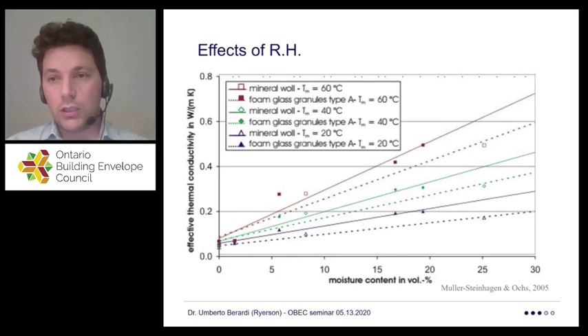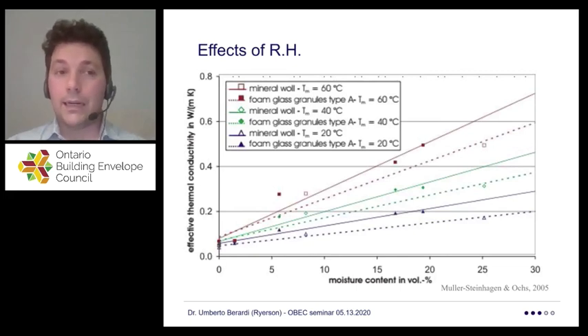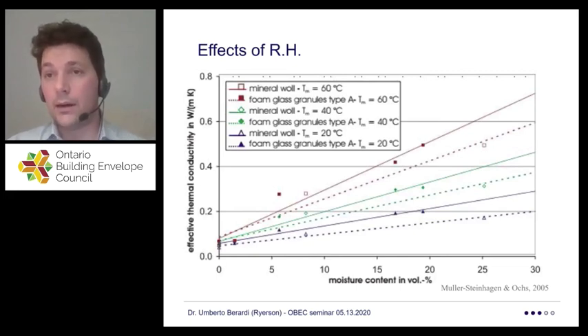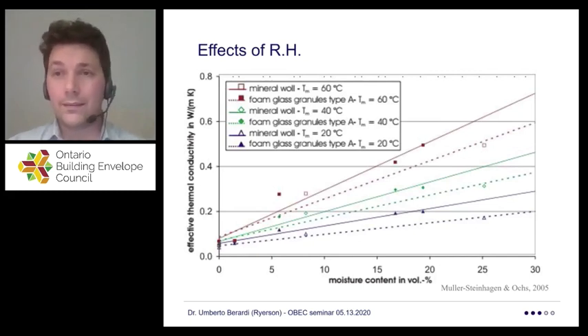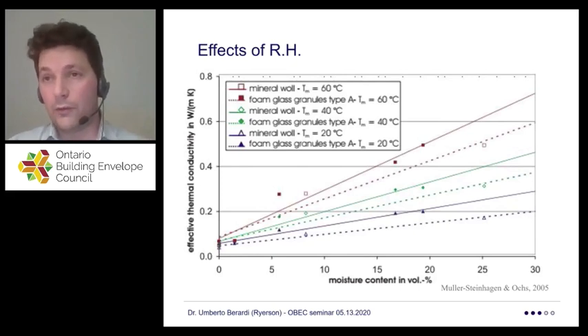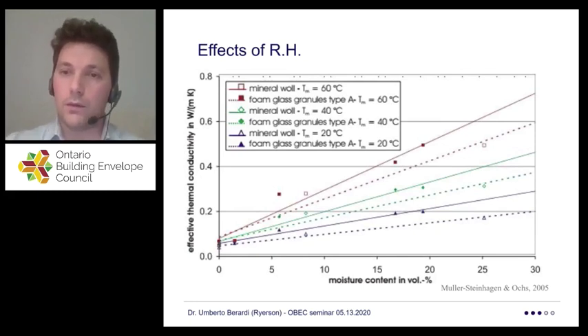the more you get moisture into the material, the more you get actually highly thermal conductive material. And this is pretty clear. And none of the materials that we can use in the construction sector will always stay dry. They always are going to be experiencing a lot of high relative humidity levels. They're going to get some moisture, and they get actually with moisture a higher thermal conductivity. Higher thermal conductivity will bring actually more heat flux and likely cool down those products and likely generate more condensation risk. So this is actually kind of a second order risk that can become quite significant for a lot of products.